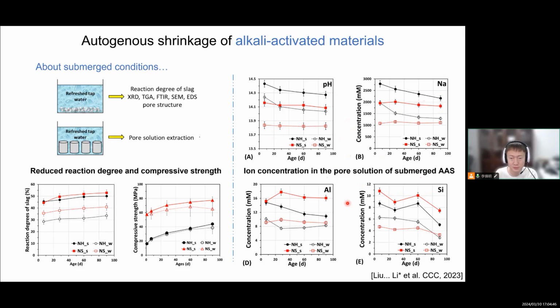The flexural strength can be even lower compared to the one in the sealed condition, and some cracking can even happen due to the leaching. So we cannot just say that using water solves all the problems. We still have to face the autogenous shrinkage problem.